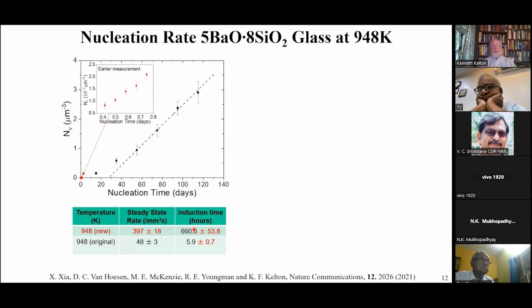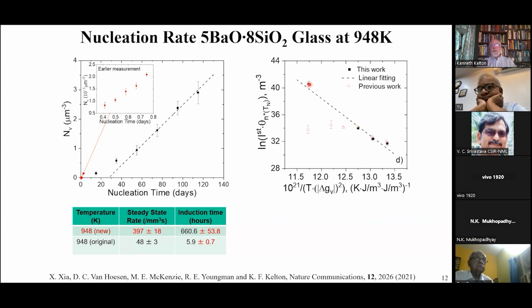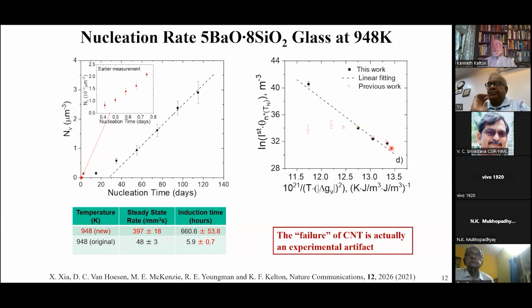So if you take these data and plot them, there's this new data point for this temperature. Here are the old data points that I showed you. At high temperatures, the old data points and the new data points agree. At low temperatures, however, this one is orders of magnitude larger than the original data point. And now we have perfect agreement with the classical theory prediction. So even though it's been in the literature for 40 years, it turns out that this failure of the classical theory is actually an experimental artifact.